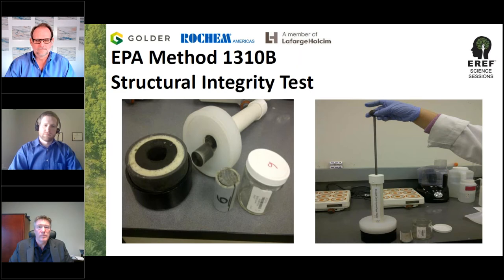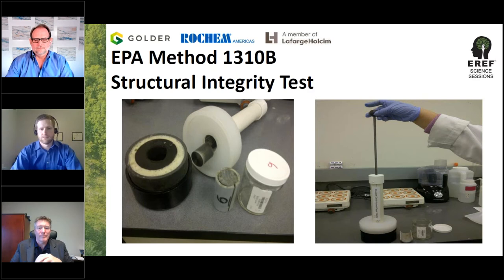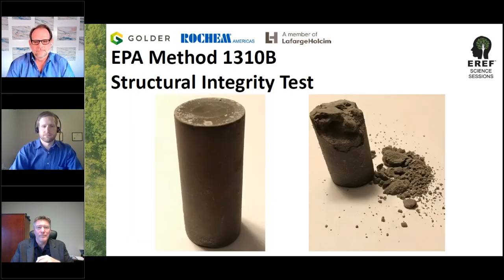At the end of 30 days, you cut it out of the mold and you put it in that compactor, which is what you see on the right. Well, you see it on the left as well as the right. It's disassembled on the left, but in the right, you have a 0.33 kilogram mass dropping 6 inches on top of your little miniature monolith. And you do that 15 times. And let's go to the next one, and you can see what happens with these.